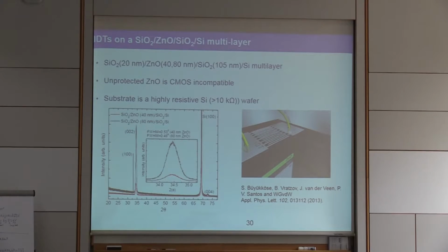Same story. This is basically what I just told you in words. Characterization here. I think this zinc oxide was sputtered at PDI in Berlin by Paulo and his co-workers. And again, also here you can see that, at least for the zinc oxide part, the 002 orientation is dominant. Of course, here now you also have your silicon peak. You have also there the capping layer. Okay.